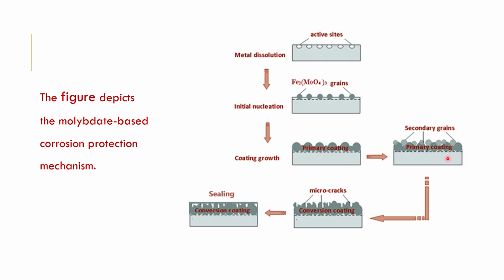That's the process. If you take the surface and watch it under a high resolution microscope, okay, SEM, you can see that we have micro cracks on the surface. So is it worth using it as it is? No. So what we have to do is fill in the micro cracks. To fill the micro cracks, we can use the sealing process. Okay. There are a number of sealing processes. Any one which is suitable for you can be done. One thing is you can give a heat treatment, or you can dip it in a bath, or you can give a paint coating on the surface. To fill the cracks, you can apply the paint on the surface.